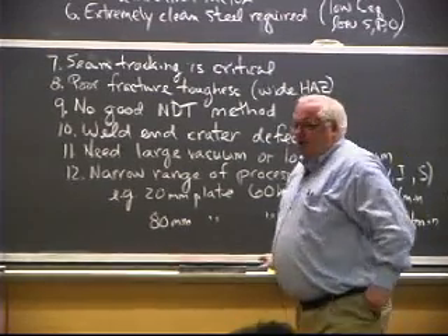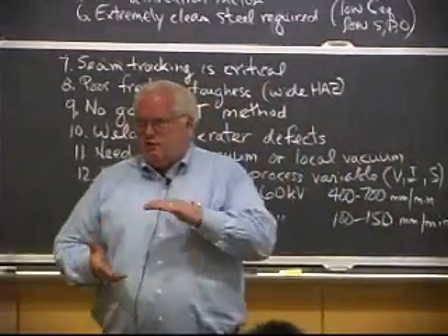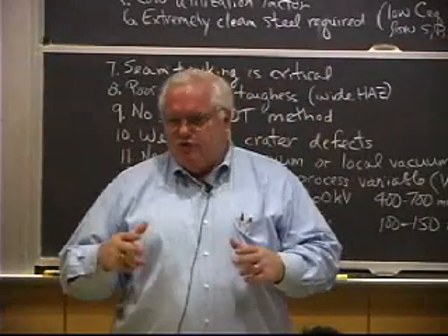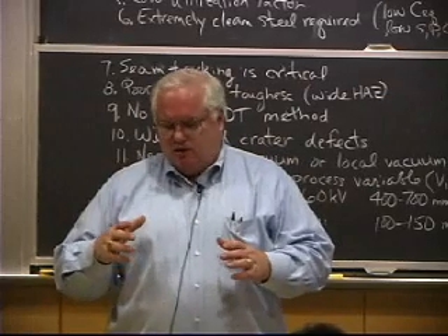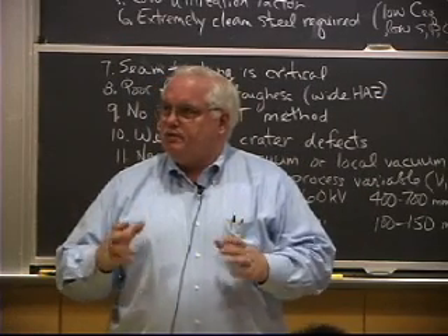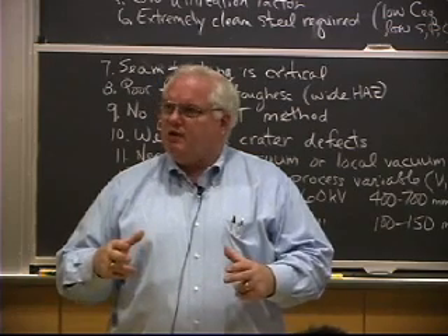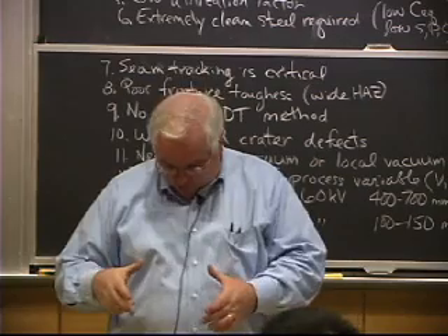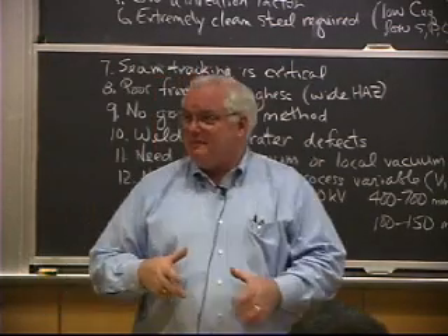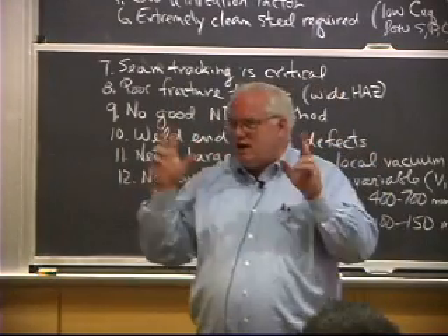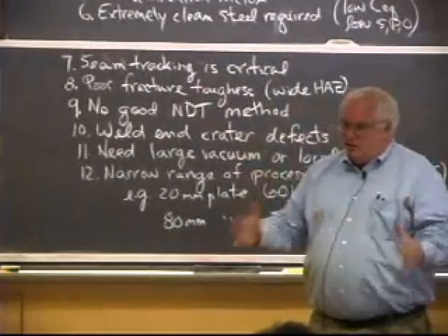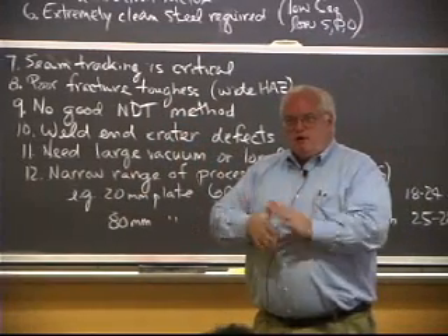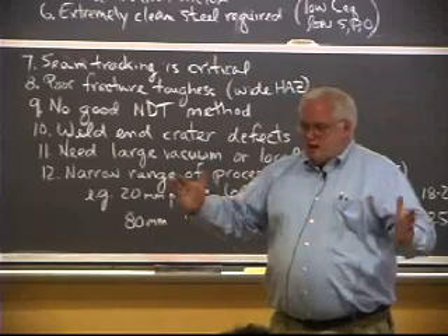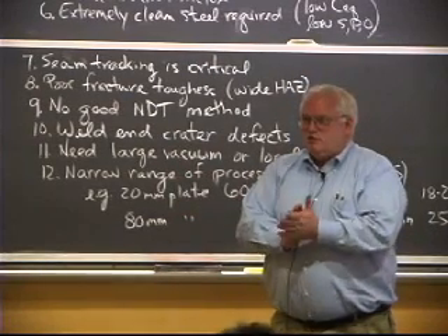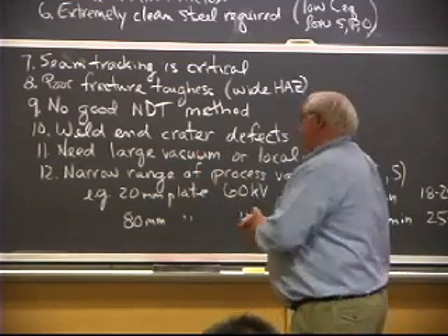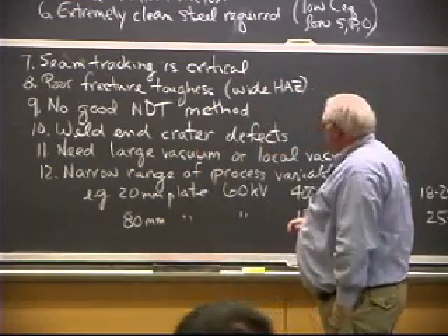In addition, heavy plate: if you look at the tightest ASTM standard for heavy plate right now, to buy it from a steel mill, it says if you do ultrasonic inspection of this plate, the largest permissible defect must fit within, I can't remember if it's a 6-inch or 12-inch diameter circle. Okay, well, wait a second. It's a pretty good sized flaw in the middle of that plate, right? But that's the best quality you can get. That's the highest standard for very heavy plate. Big heavy plate came from a great big casting. Great big castings have great big flaws from the solidification pores and defects. And they don't have a lot of mechanical working to squeeze the flaws together and weld them together, right? So you have a problem with quality of plate and other things.